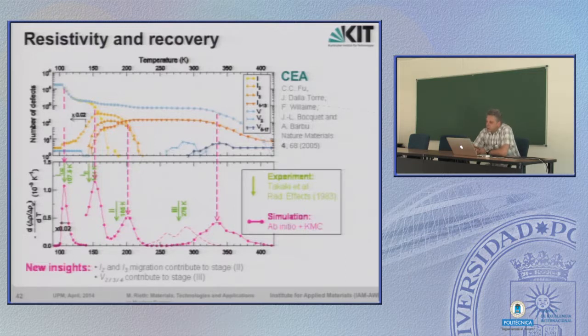And on the upper diagram, there is the number of defects. Let's first consider single vacancies, the point defects where atoms are missing. If you increase the temperature, you see at one specific temperature the curve goes down. There are fewer vacancies available, and at higher temperature the curve goes down again until we have almost no vacancy left over. The yellow curve is for single interstitials. It also goes down, but already around 180 K or so, no interstitial is available anymore.